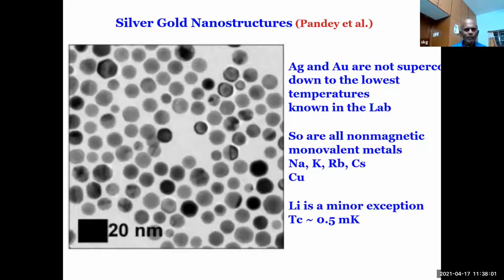So, okay, having said all this, what kind of non-equilibrium phenomena could be present in gold-silver nanostructure that Pandey and company prepared? So it's like, like a goldsmith's job. So you have gold and you put some diamond in it, or here you put silver. What kind of non-equilibrium will be there? And also, we know that pure silver and gold are not superconductors at all, down to the lowest temperature known in the lab. That's true for all monovalent metals except lithium. It's a minor exception because it has a half a millikelvin Tc.